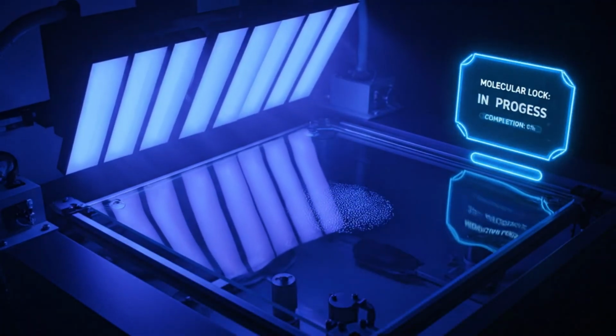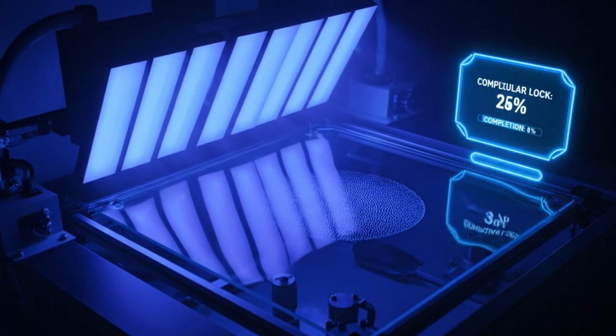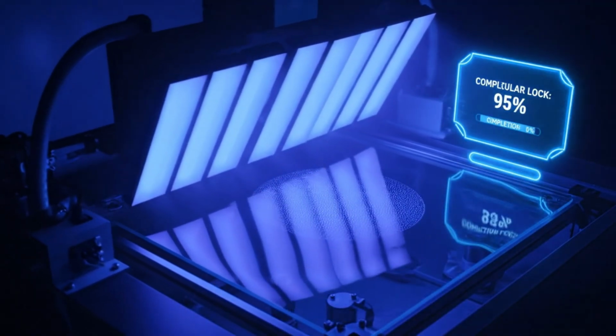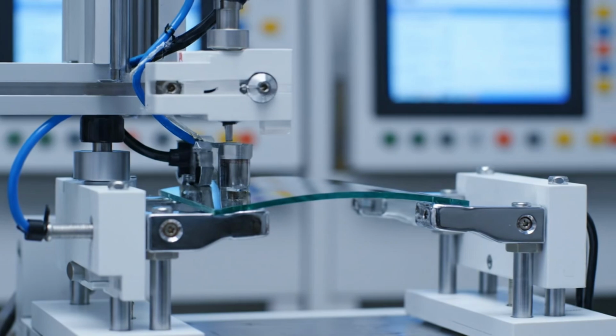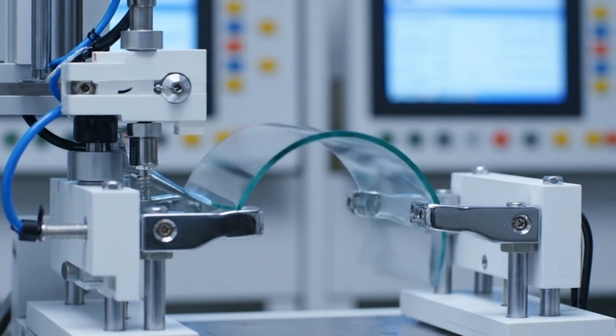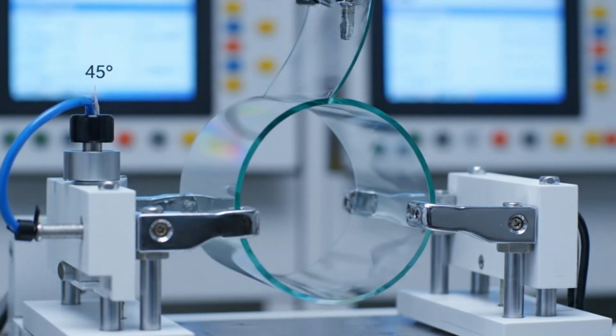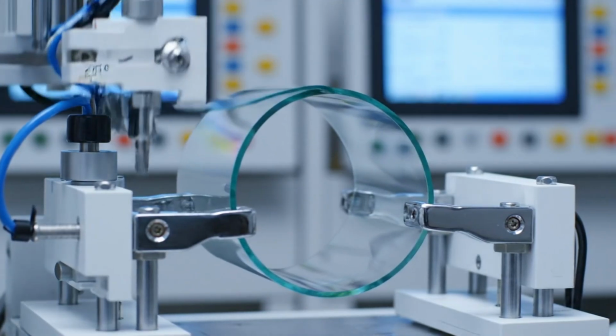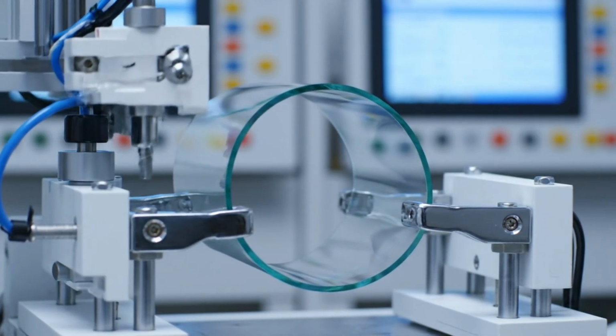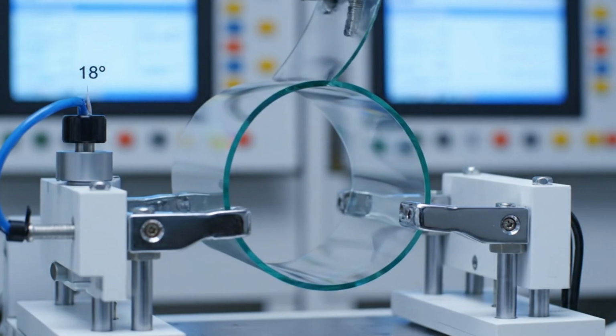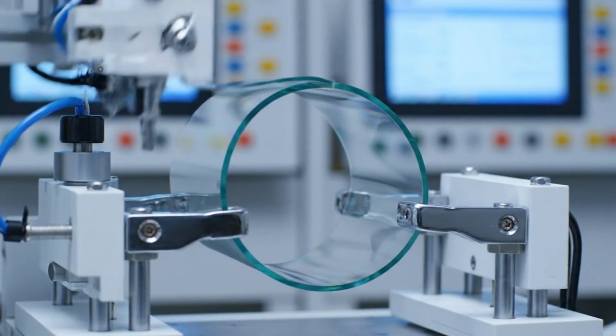The stretched glass is exposed to intense ultraviolet radiation. The UV light permanently locks the molecular structure in place. The flexibility is now built into the material itself. Every sheet undergoes rigorous flexibility testing. First, it's bent to 90 degrees, then 180 degrees. The glass folds completely back on itself without any damage.